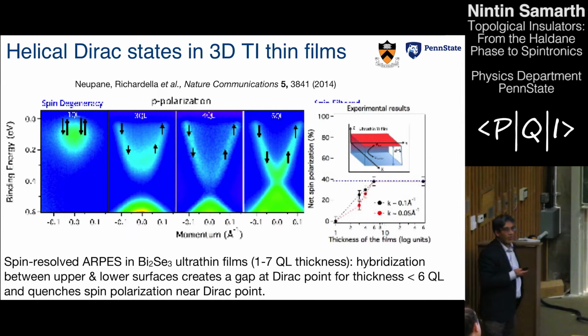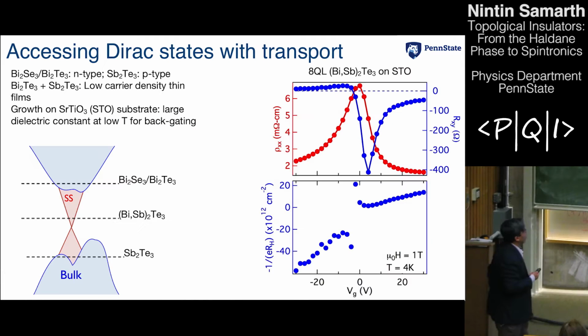And this becomes an important aspect of applying these materials for devices in a field called spintronics, because as you change your chemical potential, depending on the design of the sample, you could in principle vary the spin polarization that you're using in your devices. So it becomes an interesting knob that you can play with.